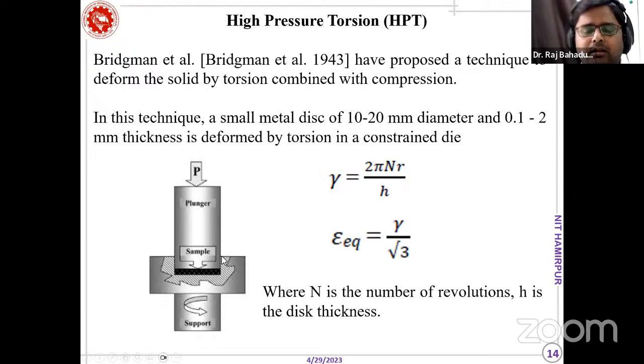But here you can impose an equivalent strain like 100, so it's like 10,000 percent, by these techniques. Because if you deform the material, the cross-section area is not going to be changed. It will remain the same, because it is in a cavity, and there's a plunger. We are rotating the plunger by applying a very high load. In that way, we are deforming the material by doing shear on the material surface, and we can calculate the strain imposed by this formula: 2πnr/h, where n is the number of rotations, r is the distance from the center of the sample, and h is the thickness of the sample.